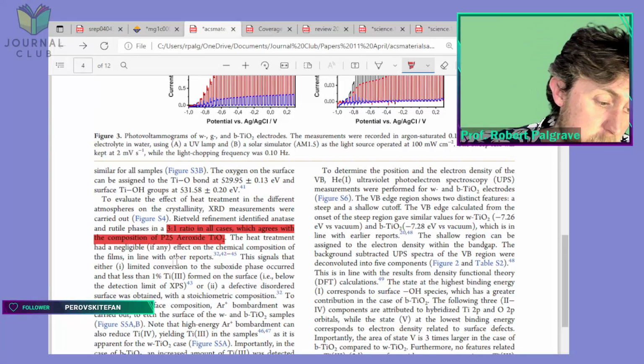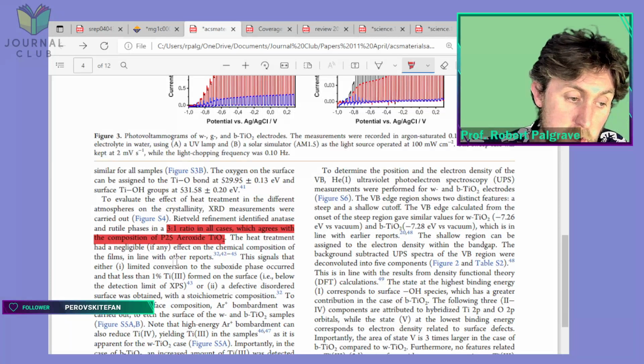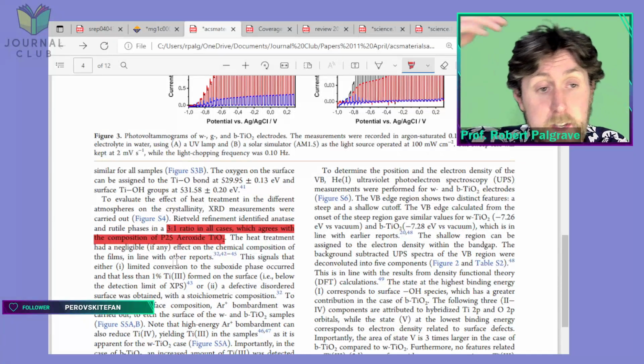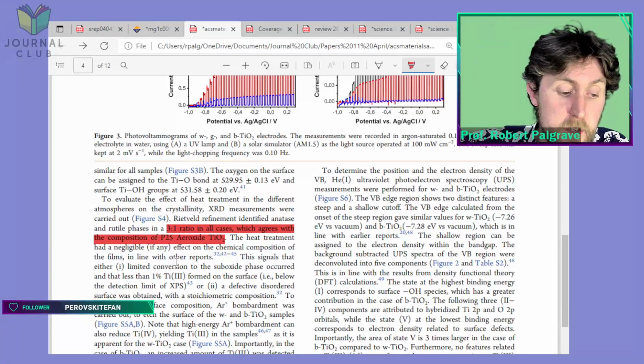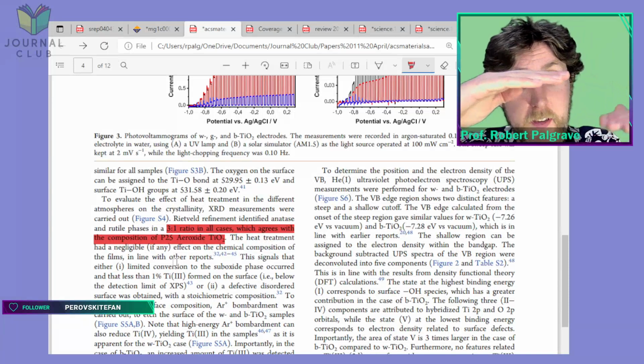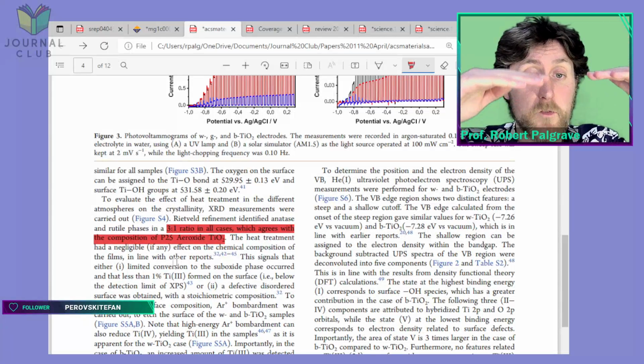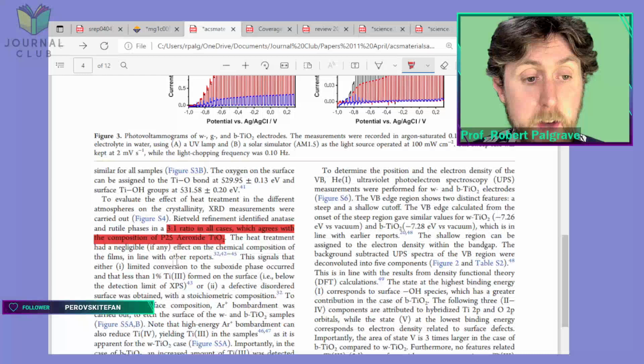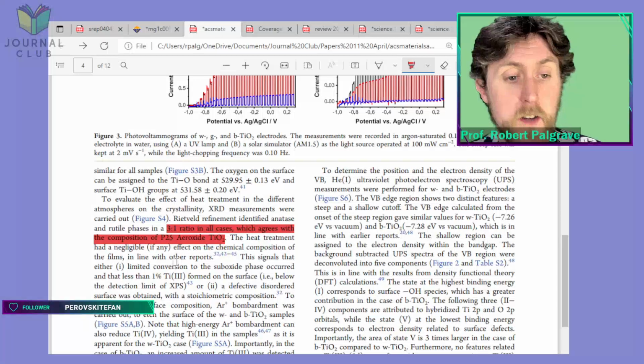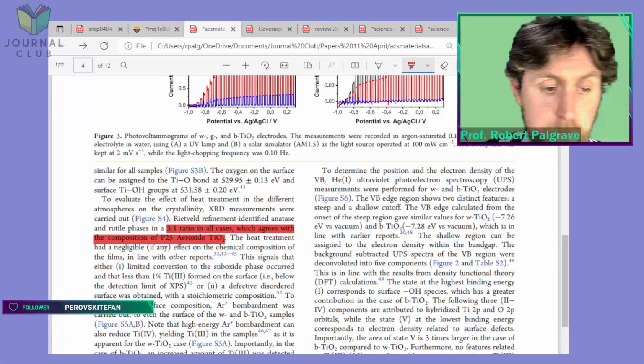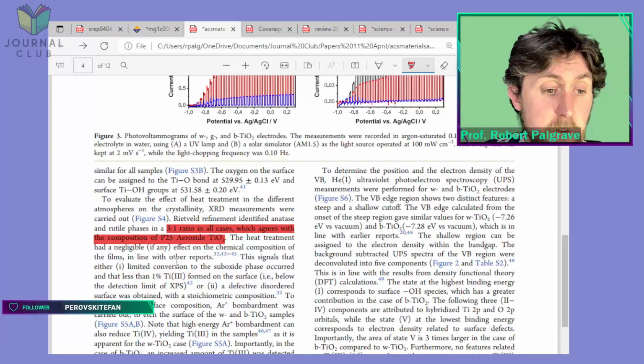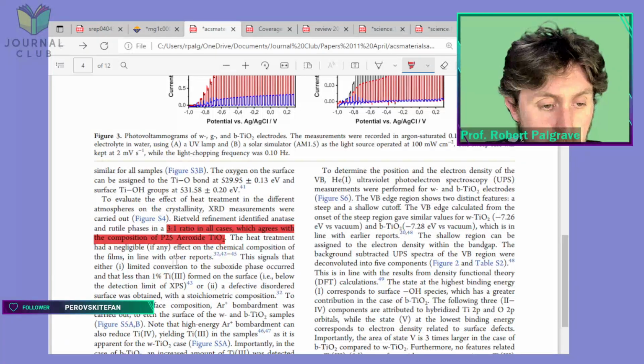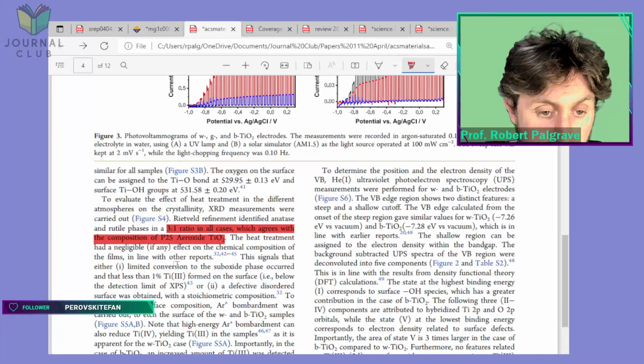So that's a nice experiment you can do. If you have some anatase TiO2, you can heat it up to progressively higher temperatures, measure the XRD pattern, and eventually you'll see the anatase start to decrease and the rutile start to increase. You can model that. It's a nice exercise to model the phase conversion of anatase to rutile, monitored by powder XRD. It's a nice way to do it.